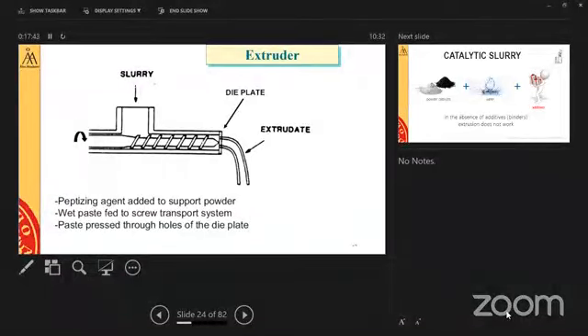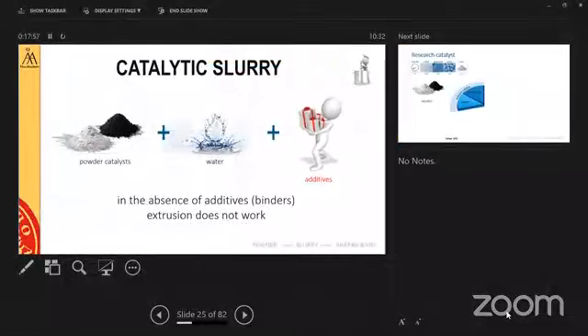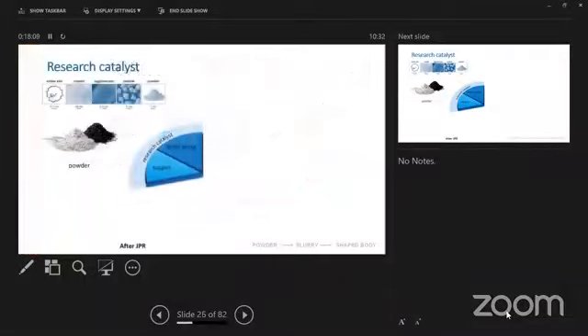So in industry, there's always a cutting device. In labs, not always, and then we cut. Therefore, quite often these extrudates have a little bit of bending shape because of gravity. So if we just use the powder and water, typically it doesn't work. We also need a lot of binders and additives to make the extrusion possible.